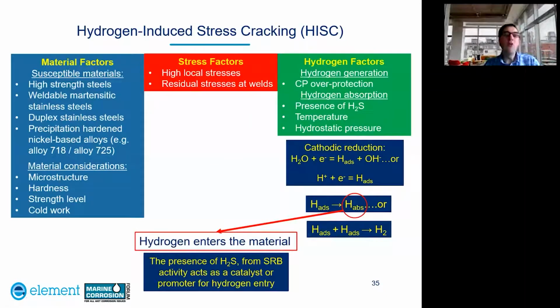So now if we look at those 3 factors in a bit more detail. So the material factor is, firstly, we need to look at what are the susceptible materials for HISC. So these are high strength steels, weldable martensitic stainless steels, duplex stainless steels, and precipitation hardened nickel based alloys such as alloys 718 and 725. Also on the material, we need to consider the microstructure, the hardness, the strength level, and if the material has been subjected to any cold work. On the stress factor, we need to look at high local stresses and if there's any residual stresses associated in particular with welds.